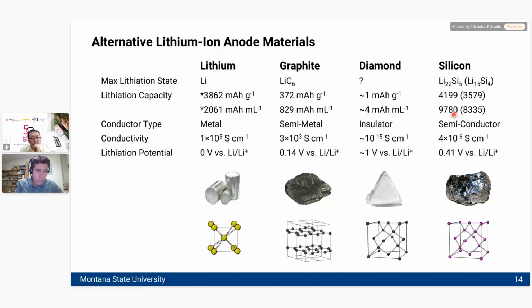metallic lithium. So there are actually two potential stoichiometries of target for lithium and silicon. One of them is Li22Si5. This has been made metallurgically, typically requires high temperatures and high pressures. The other is Li15Si4. This is the sort of realistic final stoichiometry for lithium and silicon. This is the one that you can achieve at room temperature in an electrochemical cell. And so we're going to focus on this stoichiometry in this talk. Still, these numbers are very, very high and make silicon a pretty attractive potential replacement for graphite.